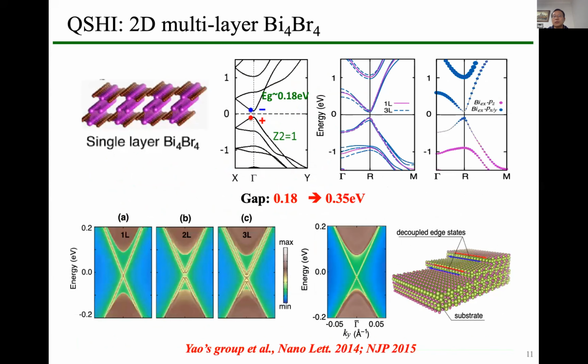So by calculation, we found that the single layer bismuth bromide can be identified as a quantum spin Hall insulator. So the gap is about 0.18 eV. For few layers, if we have two layers, then the edge states will couple with each other. Then there will be a very small band opening. So this means that the bilayer is not a topological phase. This is trivial. But for trilayer, the coupling between the three pairs of edge states still has one pair crossing the band gap. So that means this trilayer is still non-trivial.